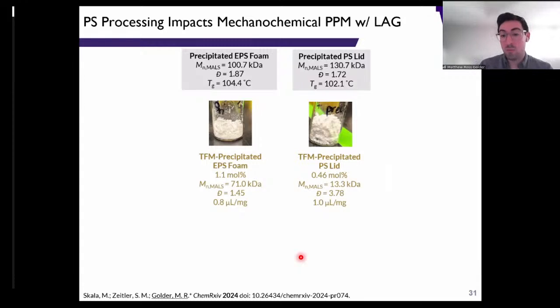Right, but when you start to apply this broadly, we actually started to notice some more problems. So we can take this precipitated EPS foam, we mill it in the presence of 0.8 microliters per mg of solvent. We see about a 30% decrease in molar mass. But when we apply the same conditions to the precipitated lid, we start to mill it and we actually end up close to the limiting molecular weight. So this tells us that the processing here of these post-consumer wastes might be a little bit different, and the broad application of these conditions across the board may be a little bit more complex than meets the eye.